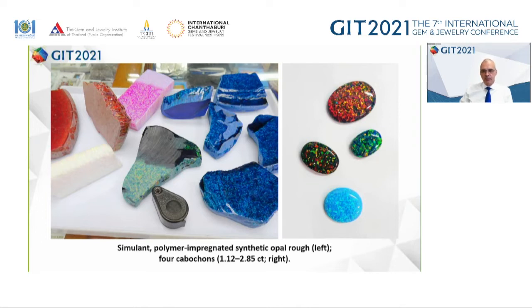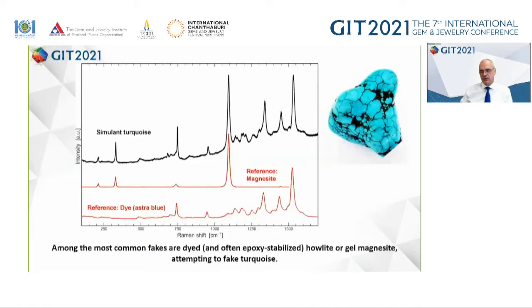A quite typical and traditional fake or simulant is that people use porous magnesite nowadays, more often than howlite, to fake some turquoise, and sometimes it's epoxy stabilized, sometimes not. You see here from the Raman spectra, in this particular case, the sample has nothing to do with turquoise, but it is a gel magnesite dyed with Astra blue.